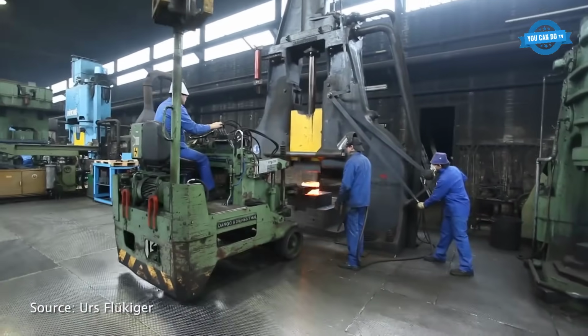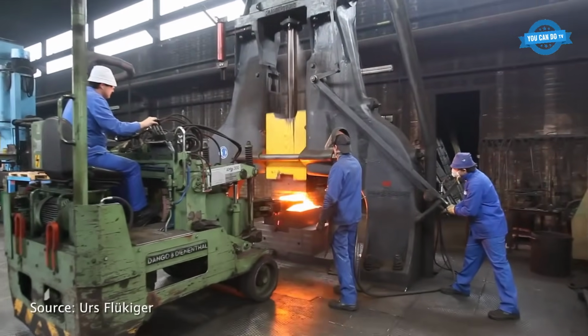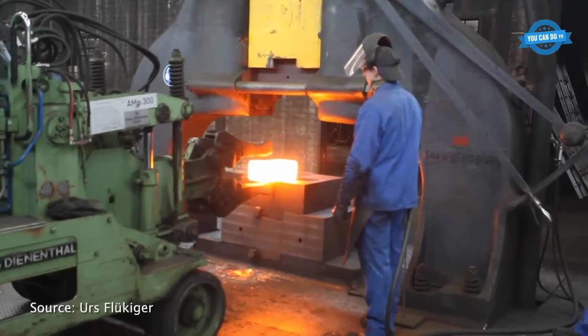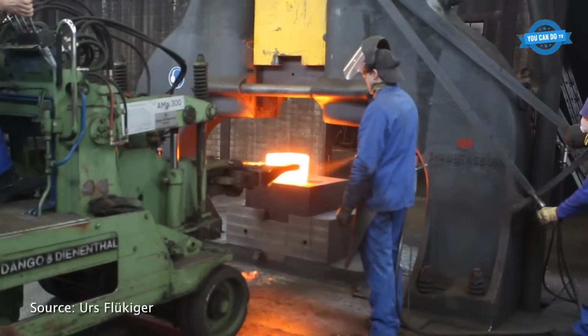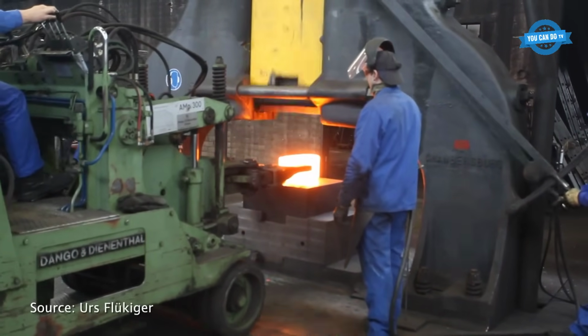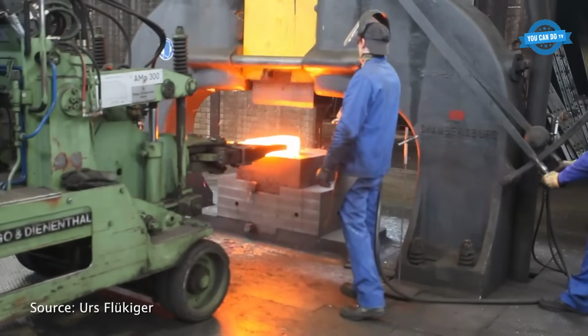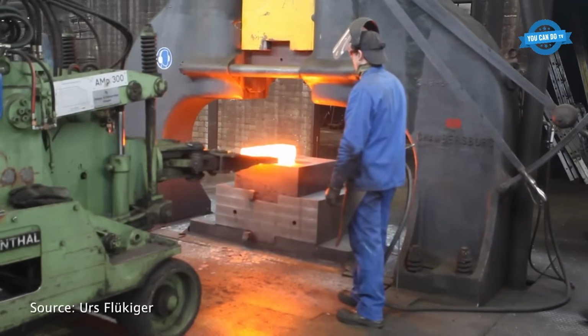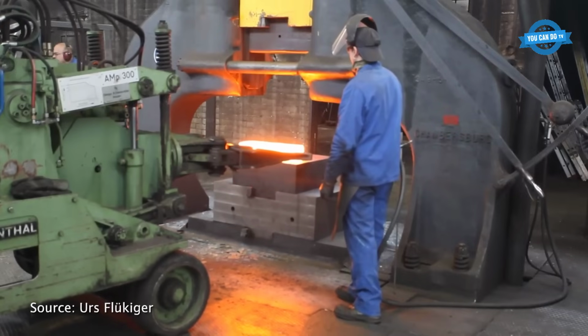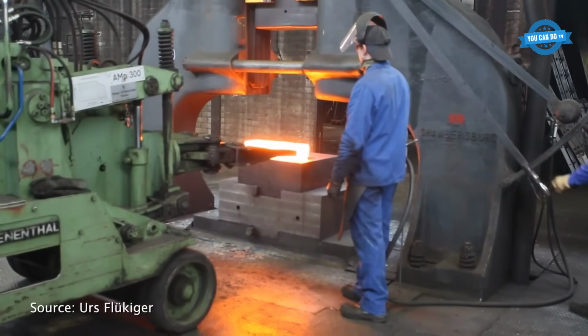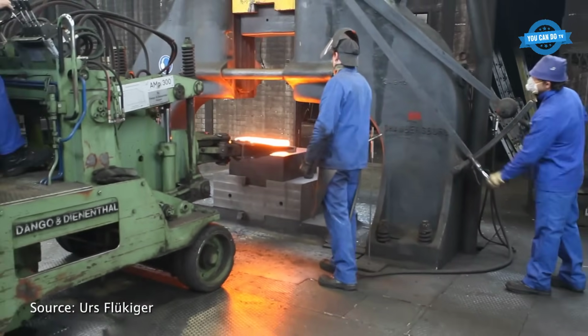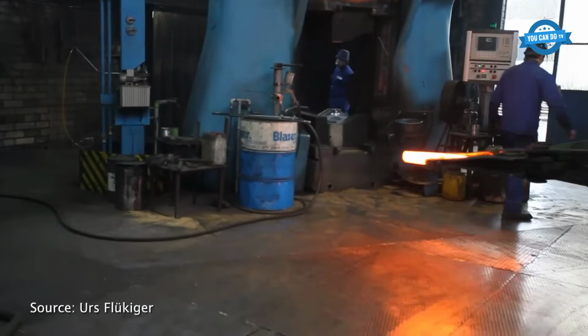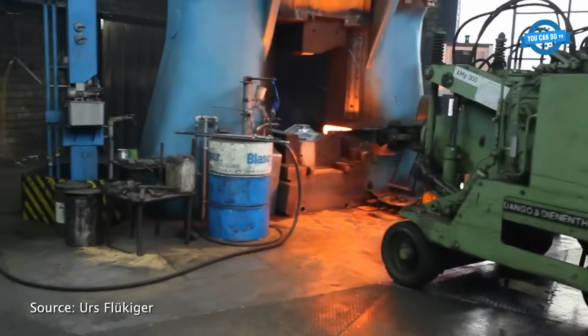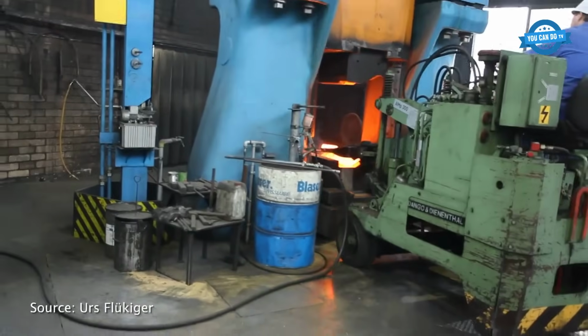Forging a railway component, specifically a locomotive chassis part weighing around 100 kilograms, begins with pre-forging using a 1959 pneumatic hammer delivering 900 kilojoules to roughly distribute the steel material. Next, an electro-hydraulic drop forge hammer from 2003, with 1,250 kilojoules capacity, shapes the part using a die, though the component exceeds the hammer's ideal size.